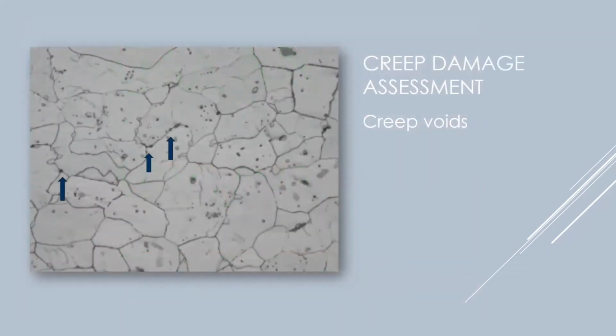The next one I'm going to go over, which is probably the one that most people are interested in, is creep damage assessments. All those blue arrows are creep voids at grain boundaries. So this is the beginning of the damage on a material for creep. In-situ replicas are the only NDE method of finding the early stages of creep damage. Now, there's a lot of people out there that say it doesn't work.